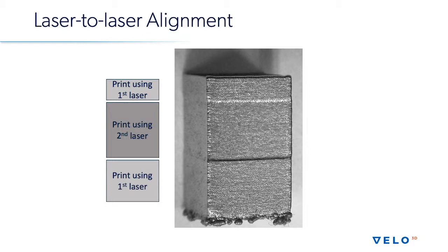And what you see is there's a shift in the second laser. One of the things that's interesting about this is if you look closely, the shift is only on one side. On the other side, it's pretty subtle. It's pretty well aligned. And this is something that we see that's indicative of chamber expansion. If your focusing optics are moving away from your build plane, the point where the 2 lasers intersect moves, and your build plane is kind of moving through your focus. That induces a shift in one axis, but not in the other. In the other axis, both of your lasers are pointed at the same point, and whenever your build plane moves, all it does is change the dimension of your part. So you'll lose dimensionality in one axis, but you'll lose overlay in the other axis.